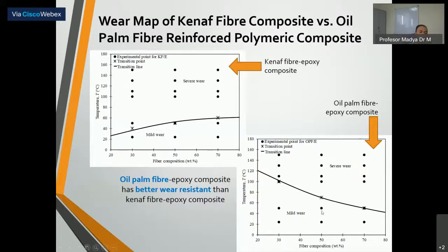From this wear map, we can see that there are two types of wear transformation, from mild wear to severe wear. And we can see from both of the wear maps that the oil palm fiber epoxy composite has better wear resistance than the kenaf fiber epoxy composite, because the severe region is smaller than the severe region of the kenaf fiber.